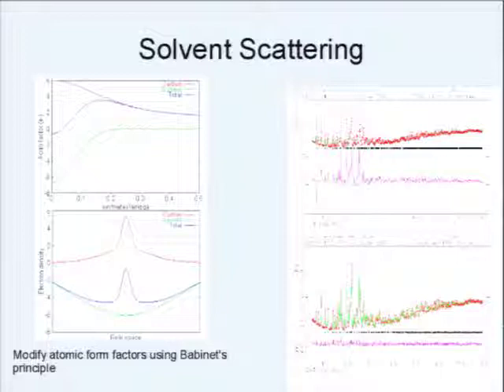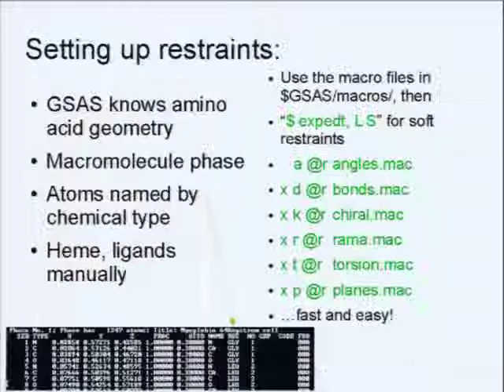If you get the numbers about right, you end up with something that starts to look pretty much like the data you record. This is really important — especially at the low angle peaks, which change a great deal. To get your fit started, you want to get your scale factor, solvent scattering, and everything else matching as well as possible before you try to refine anything inside the crystal structure, because it's a very complicated structure with many degrees of freedom.